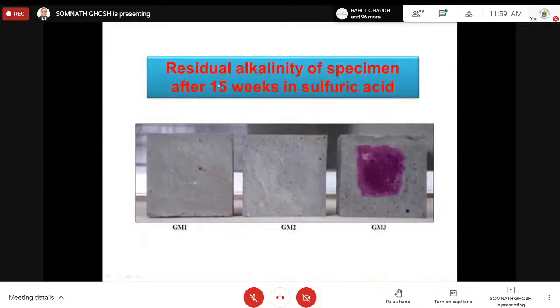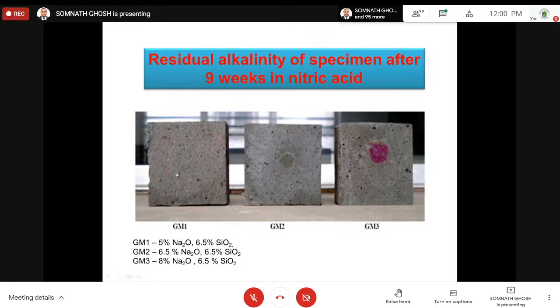You see, if you try to understand the alkalinity of the specimen under sulfuric acid, how it really reacts with your geopolymer. See, here you are seeing pink color. That means if you spray phenolphthalein, it becomes pink, meaning there is some alkali there. But slowly you see the alkali has vanished. No alkali. It is consumed by this acid. It's good. So it is good against the acid. Now, this is after 9 weeks. It is like this, after that, after that. These specimens we have done with different compositions.